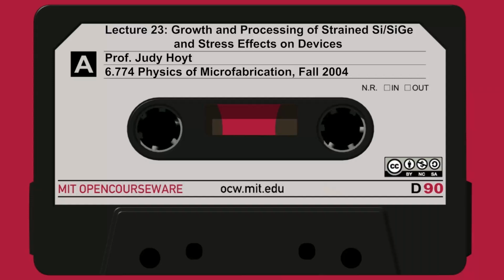For silicon germanium in a selective process, if you want to deposit silicon germanium on a wafer that has oxide on it, and little openings in the oxide where there are windows patterned so that you can reach down into the silicon, this is called selective deposition. You need to add hydrogen chloride, HCl. And this is commonly done for both the bipolar and CMOS applications. For silicon germanium carbon, you do the same type of thing, but you add one more gas, which is called methylsilane. The methyl group, the CH3, brings in the carbon, which is used to dope those devices.